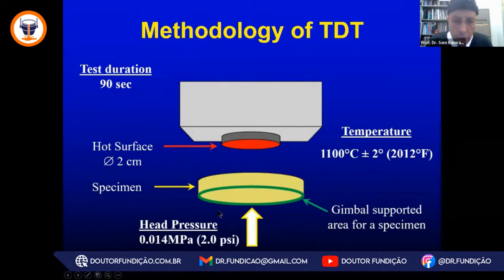The other thing that we do on this test is that we support the cookie specimen on a gimbal. The support for that specimen is only 1 millimeter around its circumference or periphery. And then we load that specimen to represent the hot surface area against the symmetrical loading at the bullseye of this specimen to represent rho GH. That is the metallostatic head pressure from which we pour that casting from the pouring basin down to the parting line.